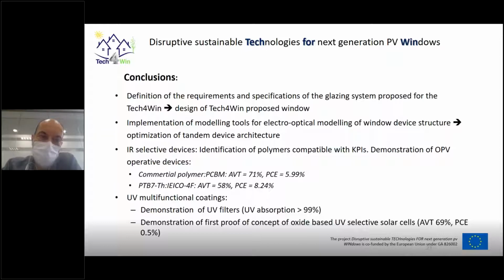But we know that for temperate or cold weather conditions, we need to introduce a gap in the window structure to obtain the required thermal insulation level. So it would mean a more complex, double glazing structure. We have also implemented the modeling tools for the electro-optical modeling of the window device structure, and this is important to optimize the device architecture, because we have to put a very high number of layers, but in the end, all these layers must not compromise the level of transparency. We have to keep the transparency level higher than 60%.